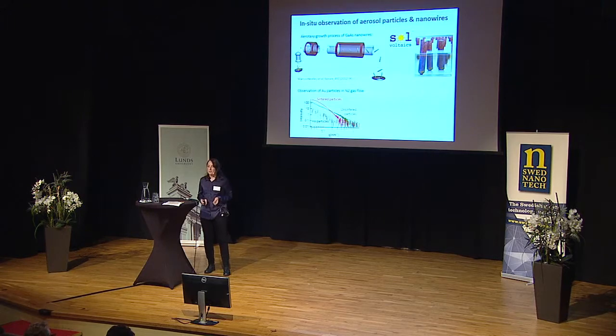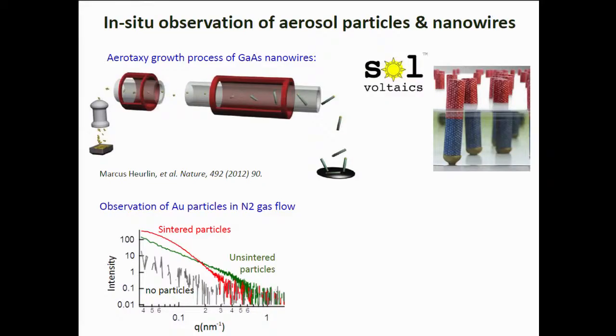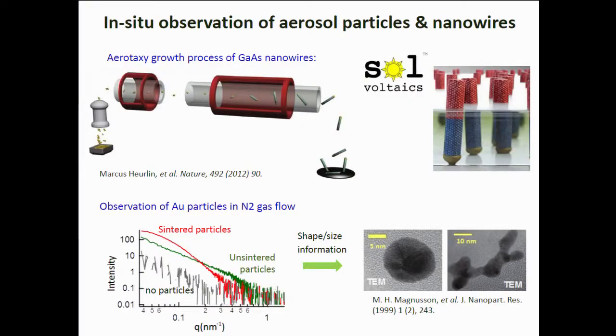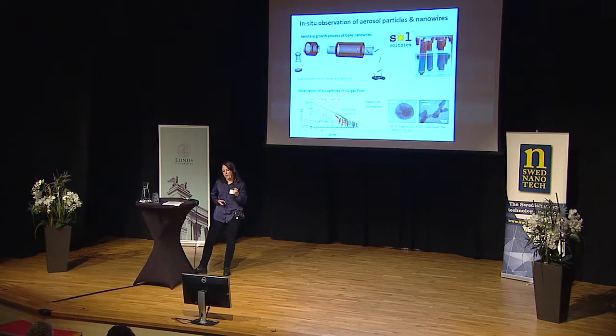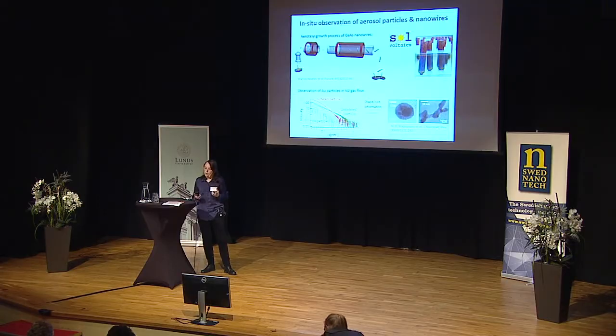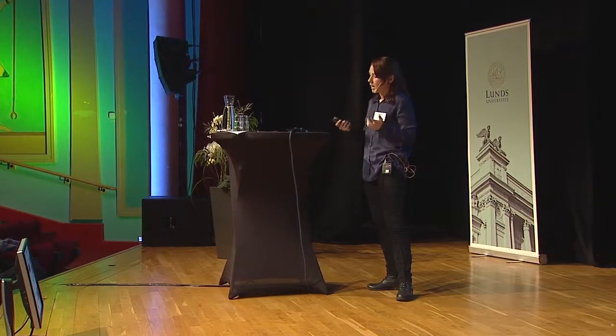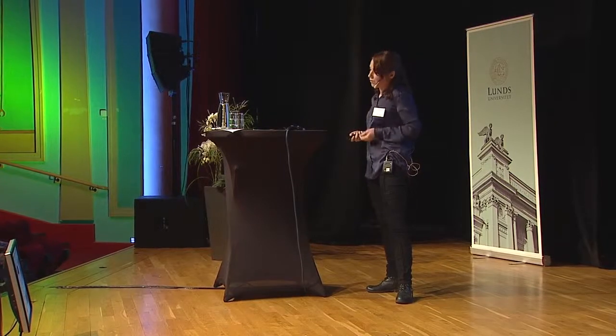So far, what we've been able to achieve in this project is to use small-angle scattering to characterise the catalytic gold particles in real time while they're flowing through the flow reactor in nitrogen gas. Using this technique, we can extract information about whether the heated particles are nicely spherical and round and obtain their average size, or whether you have clumping and clustering of irregular particles. This is a means to really observe in real time, in-situ, the as-produced particles without being exposed to any outside air.